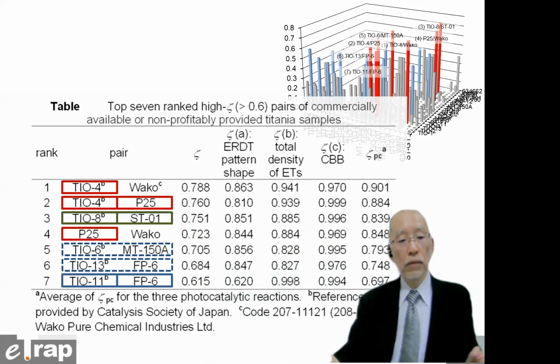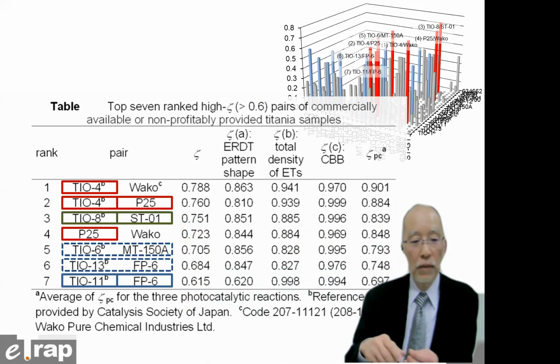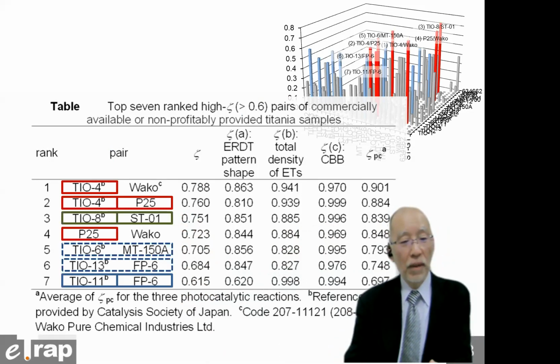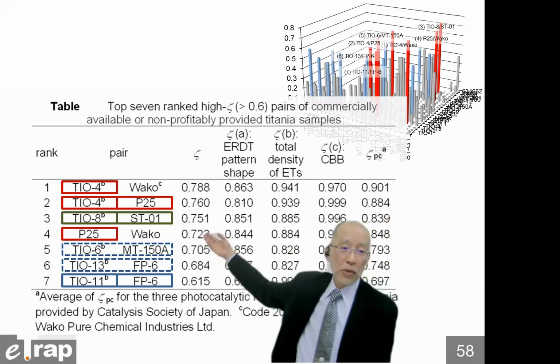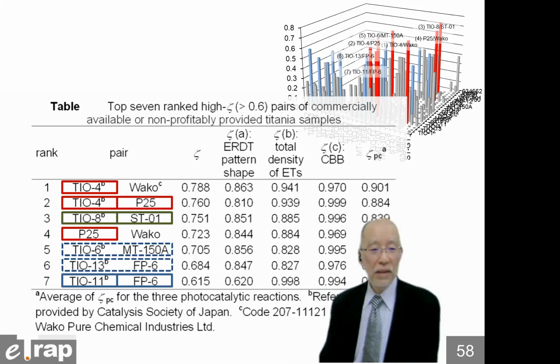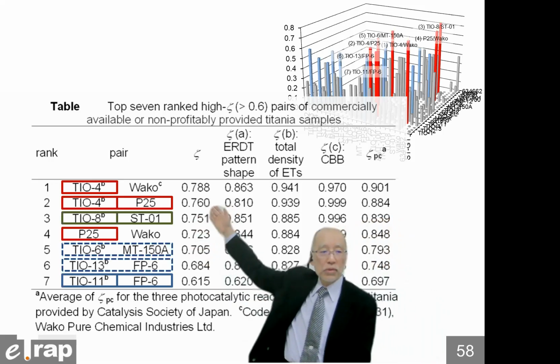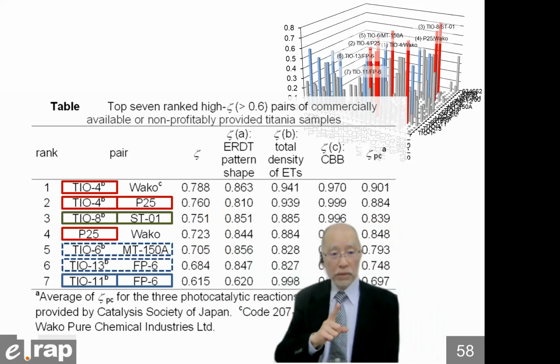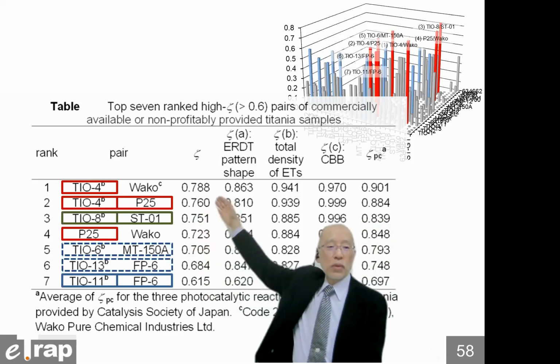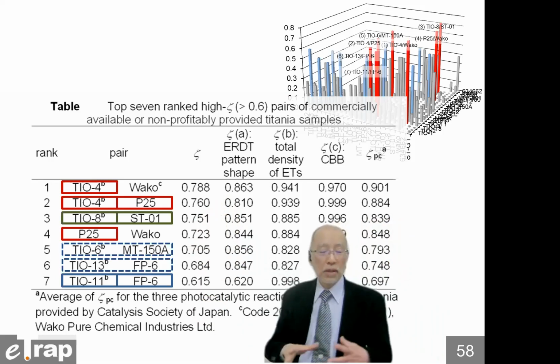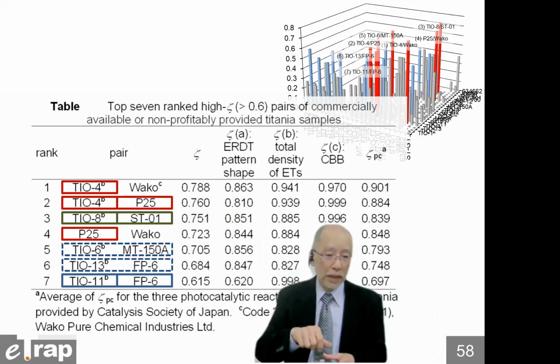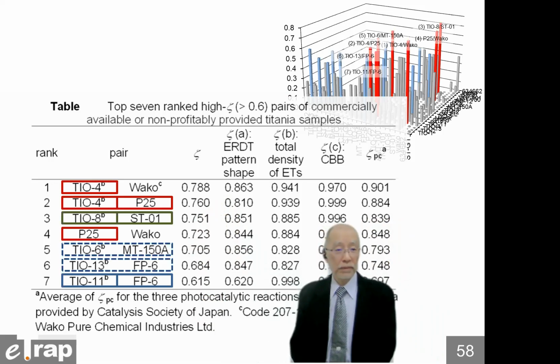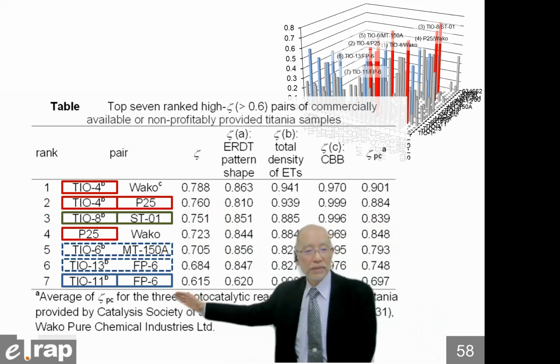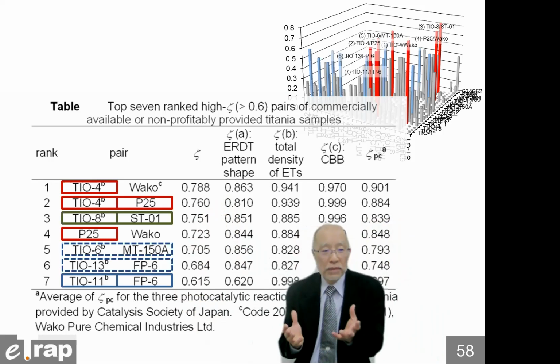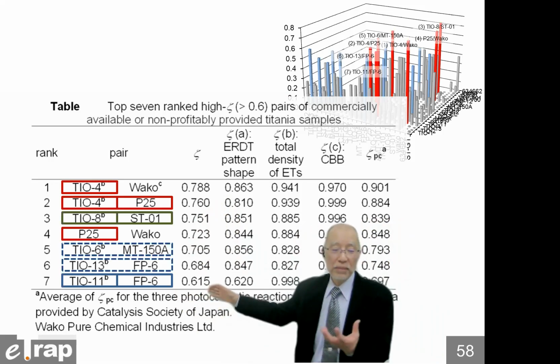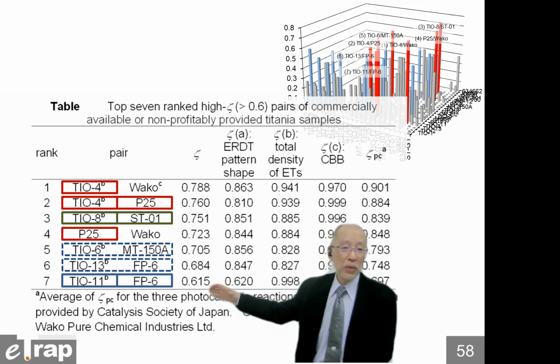They are provided in different ways, but that is the same product provided by different organizations. So we know that TiO4 is P25, the source material is the same. And therefore, it is natural to see the high degree of coincidence of those rank 2, rank 3, and rank 7. But that is actually lower than 0.9, which is provided by the samples taken from almost the same portion in the same bottle. And for this pair, TiO11 and FP6, even though they are the same product, it is not so very low, but relatively low degree of coincidence.